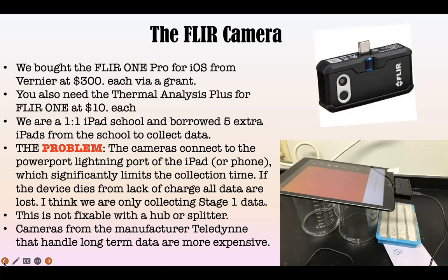They were pretty good about that. The one team that had problems on that noted it, and the class did a good job of thinking about how that would affect their temperature profile and what that would mean. What they did discover is that the groups that had a bigger temperature drop had stronger mortar bars. It was not as strong a correlation. There were exceptions, but most classes could conclude that.